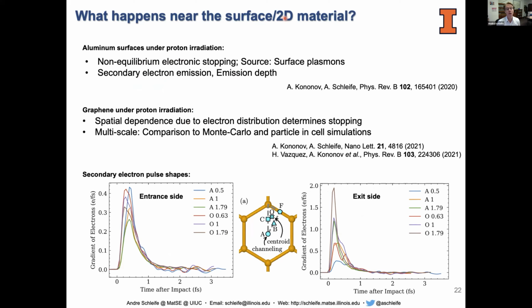The reason we used aluminum is we had very reliable bulk data, and the interesting result was actually that for very thin aluminum, we believe that we see the effect of surface plasmons created by the incoming excitation on the energy loss that the projectile experiences as it moves through the material.